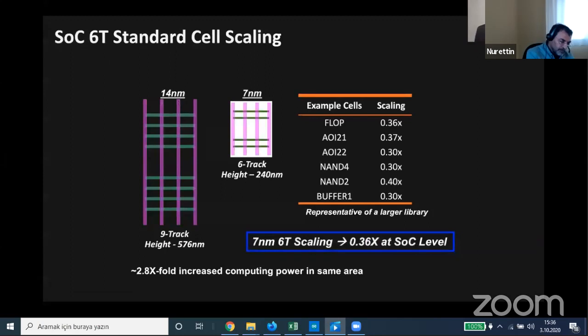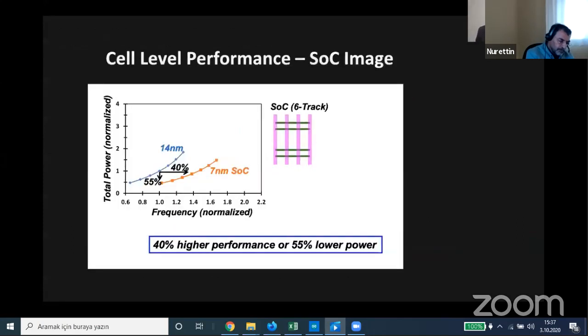So we use this concept to scale from 14 to 7, and we were able to scale our standard cell by a factor of 0.36x, or in other words, that ends up being almost 3 times more computing power for the same area, which is very significant. In terms of the electrical measurements, these are actually high-frequency ring oscillator measurements, and this plotted here is the frequency versus power. We achieved, comparing to our 14 nanometer technology, 40% higher frequency at the same power, or at the same frequency, 55% less power.